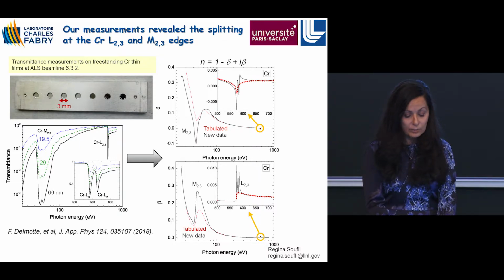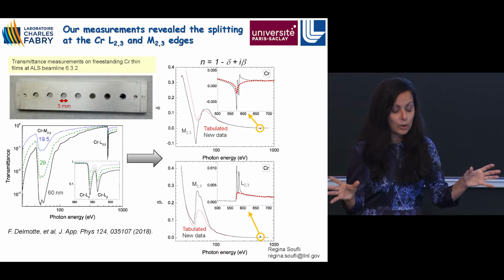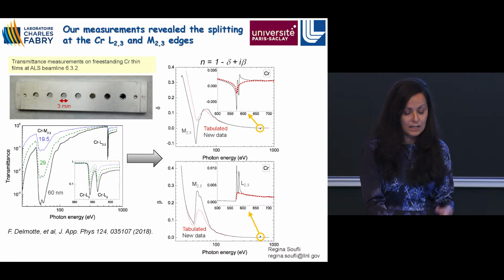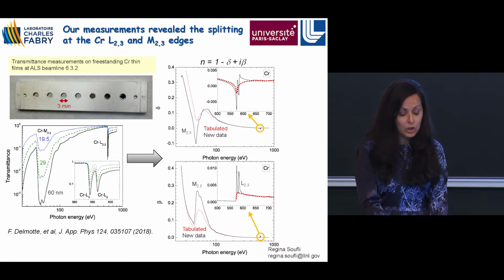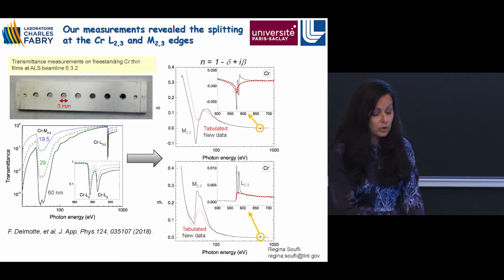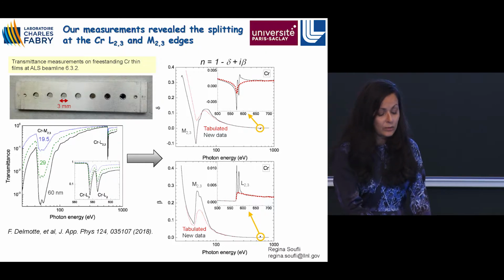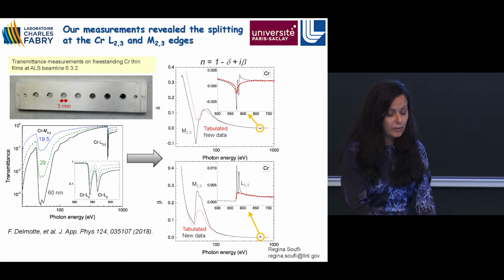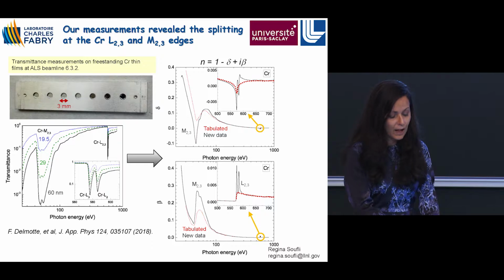And from those data, you obtain directly the absorptive part of the refractive index, beta, and then you combine them with other absorption data outside the range of the measurements, and you do an integral transformation, Kramers-Kronig transformation, to obtain the real part of the refractive index, which is delta. And so it's pretty complicated, and it takes a lot of work. But we succeeded. And in this fashion, we were the first to demonstrate the splitting in the L23 edge of chromium and also in the M23 edge of chromium. And you can appreciate that there's a difference of up to a factor of 3 between the old tabulated values and the new values.